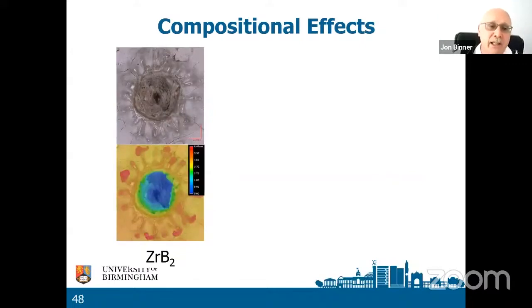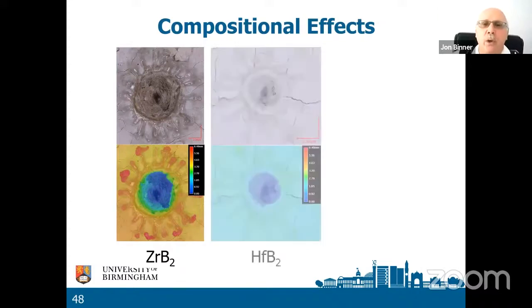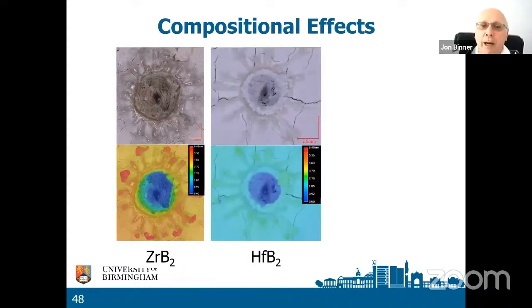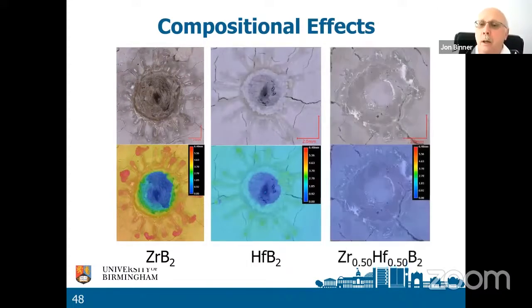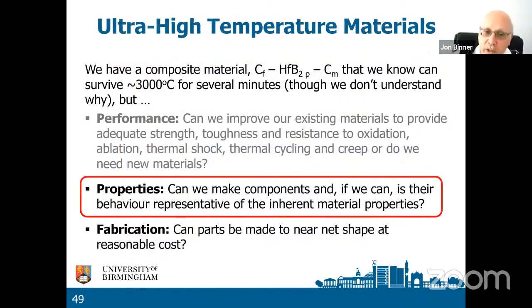And you can see that's what the sample looks like. You can see those splashes of molten zirconia. With hafnium diboride, it's broadly similar, but with that mixture, you get a different pattern, and we need to understand that pattern. Okay, so performance, we can achieve quite a bit.